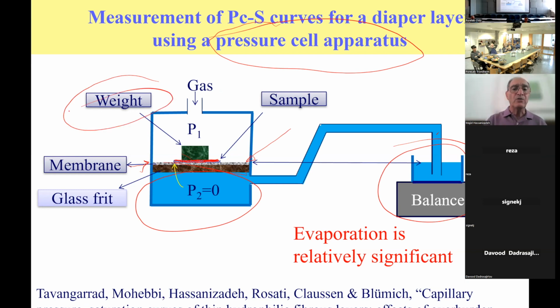We put a weight there, about 14 PSI, to mimic a baby sitting on the sheet. And then you can do drainage and imbibition measurements. For example, if you want to do drainage, you start with a sheet put there and let it fill up with water, and then increase the gas pressure in order to eject the water from the sample. You can also do imbibition, of course, where you start with a dry sheet at very high gas pressure and then decrease the gas pressure slowly to let the water come in. You can do that in steps and measure the capillary pressure saturation curves.